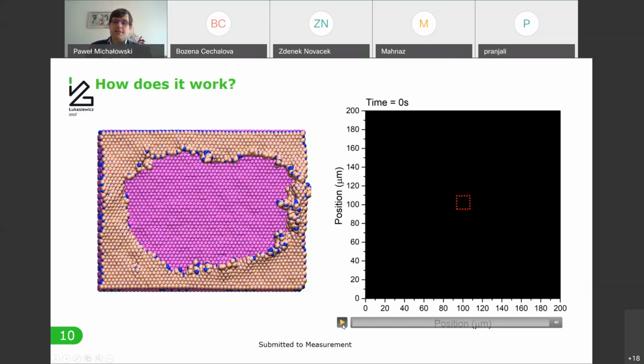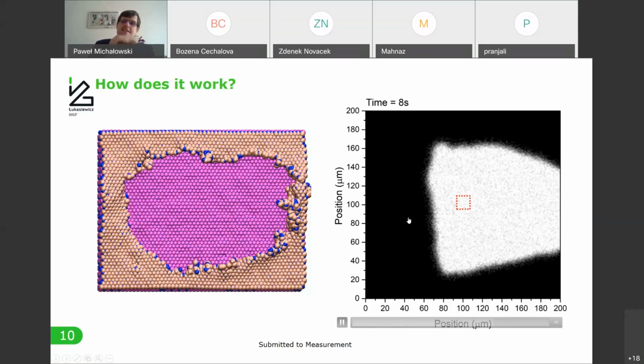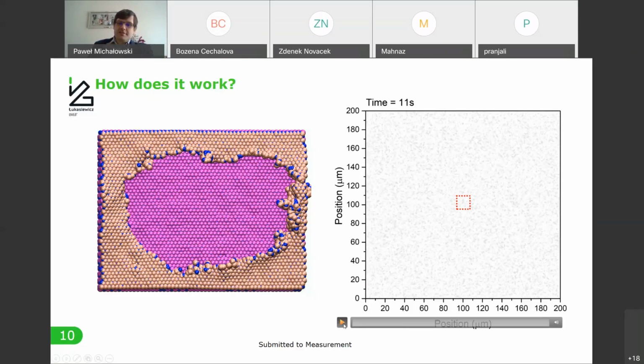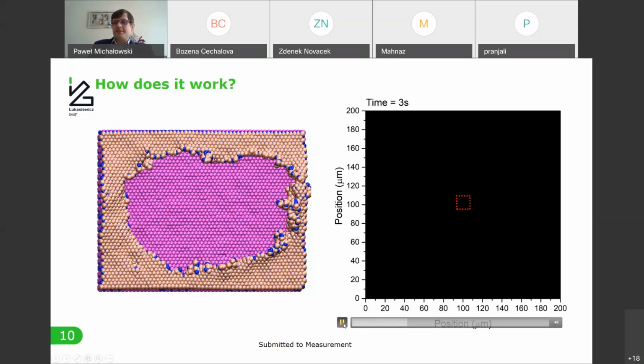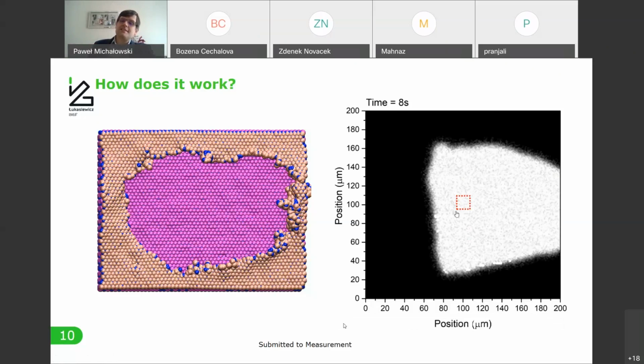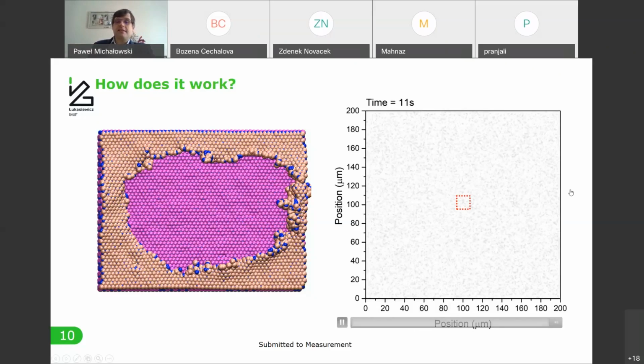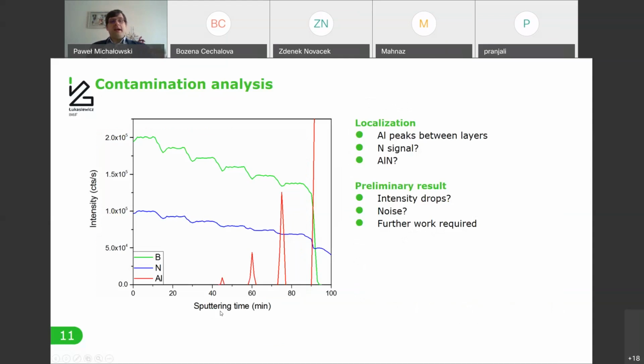Then when I start such an experiment, at the beginning there is absolutely nothing. After 8 seconds, I expose this region, but then when bombarded from left to right again, I see exactly the same effect. If I run it again, you can see that the sputtering process is once again proven experimentally anisotropic, and it's much faster in the direction of incidence than in any other direction. This way we proved how you can sputter one layer without causing any damage to the bottom one.